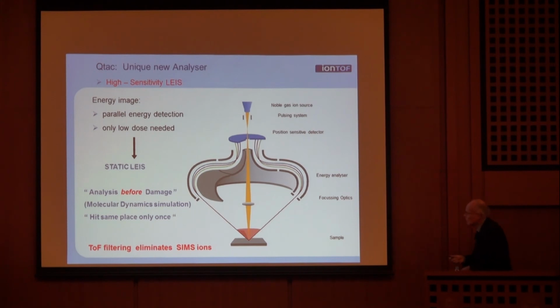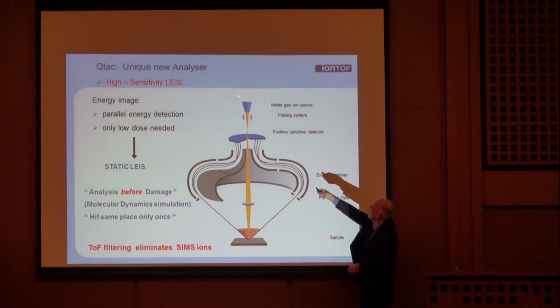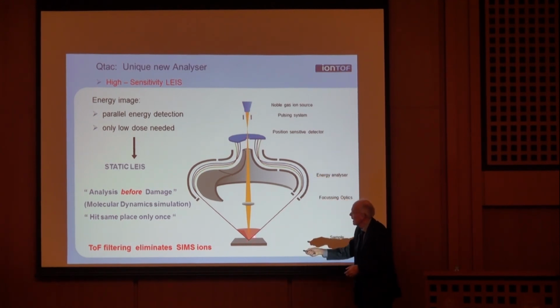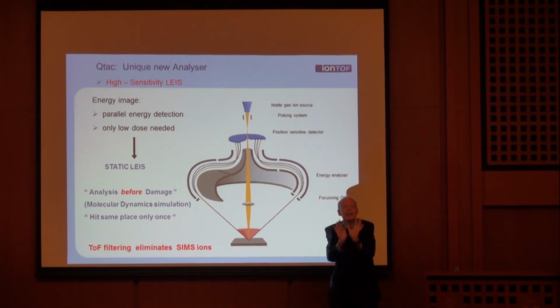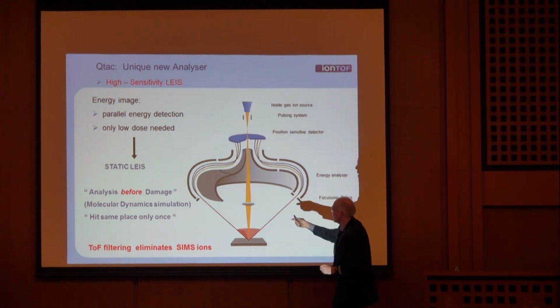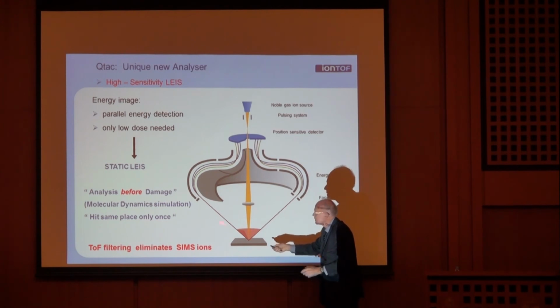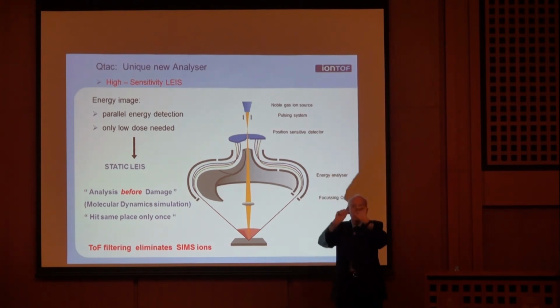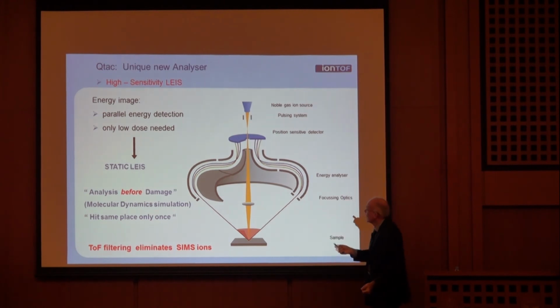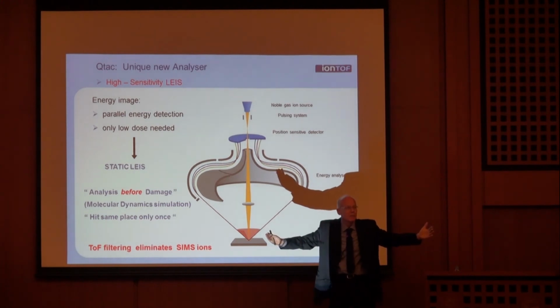How does it work? Well, you make ions here in an ion source, you accelerate them, whoop, whoop, whoop. They hit the sample and they scatter back. So they come in and you scatter back in a cone. And because it's a cone, they all have the same scattering angle. And you collect a lot of the ions. Then, when the ions scatter back, this is an electrostatic field. Fast ions go to the outside, whoops, and end up here. Slow ones are deflected. So here at the end, I get a spectrum in energy.